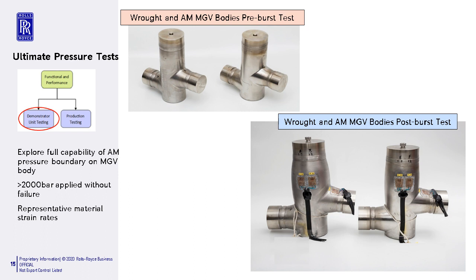During each test, we also took strain gauge measurements at 2 locations that proved both materials and manufacturing methods had representative strain rates against the increase in pressure range.